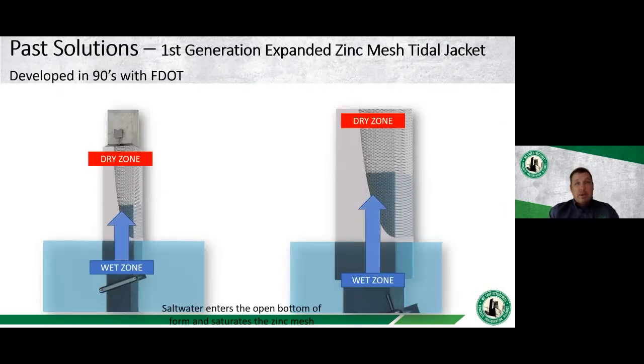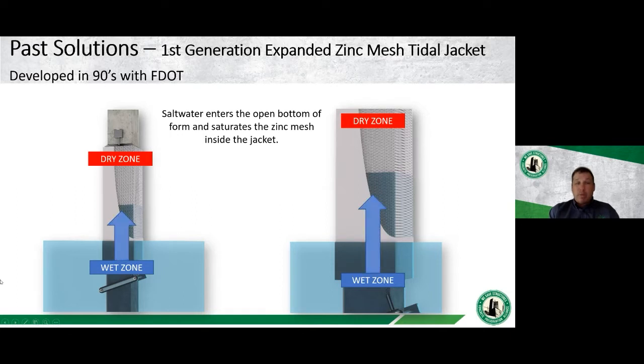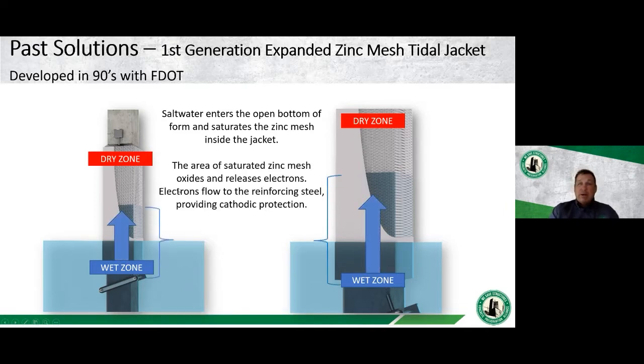If we move on to here, you can see that our salt water enters the bottom of the jacket, and the salt water in the tidal zone goes up and down. So we have that salt water traveling up and down inside of the fiberglass jacket, and it's going to saturate that zinc mesh inside of the jacket. The area that comes in contact with the zinc mesh is going to corrode or oxidize, and as it oxidizes, it's going to provide protection to our reinforcing steel within our pile. So the electrons are flowing to our reinforcing steel. Our zinc is cathodically, or galvanically, protecting our reinforcing steel within the pile. It's just a sacrificial system relying upon the dissimilar metals.